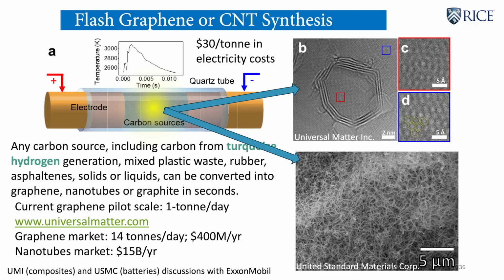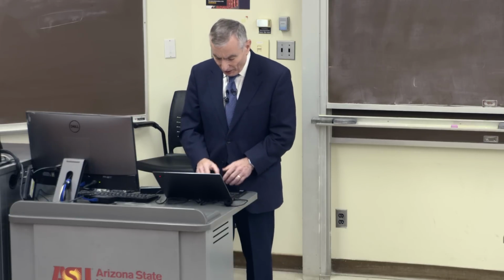If you add an iron source to this, so say you add ferrocene to the plastic and you flash it, instead of getting graphene, you get carbon nanotubes. Because carbon nanotubes form at a much lower temperature, because it's a catalyzed growth, it'll catalyze the growth off of those iron atoms, and you get carbon nanotubes. So we've started another company around that.